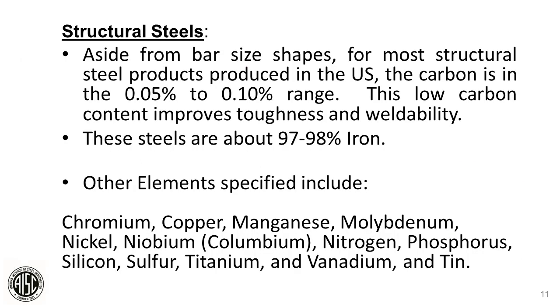So how do you define structural steels? For us, we describe it as aside from bar size shapes. For most structural steel products produced in the United States, carbon is in the 5 to 10 carbon range. We typically talk in points. We call it 5 to 10 points of carbon. This low carbon content is very good for toughness, ductility, and weldability. Of course, you get about 97, 98% iron.